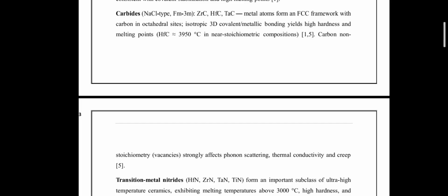The carbides of transition metals such as zirconium carbide, hafnium carbide, and tantalum carbide crystallize in a cubic NaCl type structure, with the metal atoms forming an FCC lattice and the carbon occupying octahedral sites, which are the interstitial sites of the FCC structure. This structure produces isotropic three-dimensional bonding, leading to extremely high hardness and melting point, with hafnium carbide approaching 3950 degrees Celsius in nearly stoichiometric composition. However, carbon vacancies are common and strongly influence thermal conductivity, phonon scattering, and high temperature creep behavior.